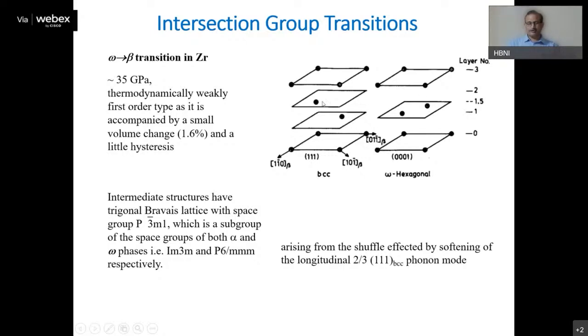So there is a clear-cut pathway for the omega to beta phase transition, and for that one has to consider that there is no group-subgroup relationship directly. So we have to consider another space group, which is related to both the initial and final space group. It has been shown that this intermediate structure has a space group of P3m1, and this is a subgroup of both the alpha and omega phases.